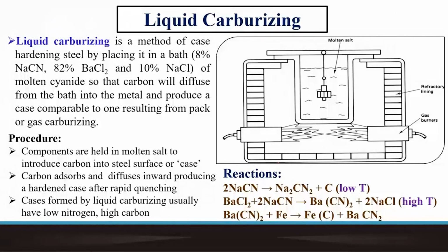So what it means essentially is that unlike the previous case, where we conceptually had a box and the component was packed inside with a box filled with certain solid charge, which we said the pack, and the pack comprised primarily the charcoal or carbon containing material or coke, and then barium carbonate or one of those carbonate materials which can decompose and produce carbon dioxide at high temperature, and maybe some catalyst and some sand and some other packing material. So the entire process was solid state, and it was filled up inside the box containing single or multiple such components which were to be carburized.